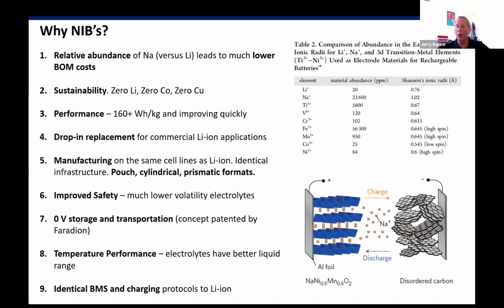So the guys on the manufacturing line for the cells don't see any difference between changing from lithium ion to sodium ion. The only thing you'll note is that, instead of having one copper current collector and one aluminium current collector, it's aluminium on both sides. And we can make pouch, cylindrical, and prismatic designs, right? So those are the ones that are currently used in commercial lithium ion. As for Faradion, we make some of each of those formats, mainly pouch, but we also make cylindrical and prismatic.